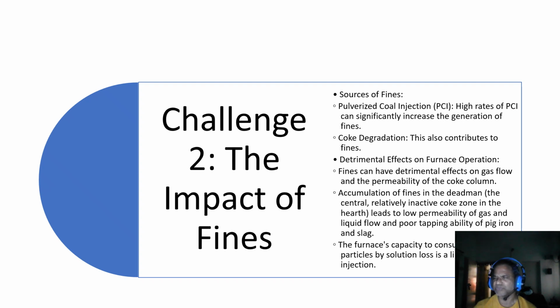Additionally, coke degradation within the furnace also contributes to the amount of fines. The detrimental effects of fines on the furnace operation are manifold. They can severely impede the gas flow and the permeability of the coke column. A major problem arises from the accumulation of fines in the deadman, which is the central, relatively inactive coke zone in the hearth. This accumulation drastically reduces the permeability of both gas and liquid flow, leading to poor tapping ability of the pig iron and slag. The furnace's inherent capacity to consume these fines through the solution loss reaction is limited, which puts a ceiling on how much coal can be injected.